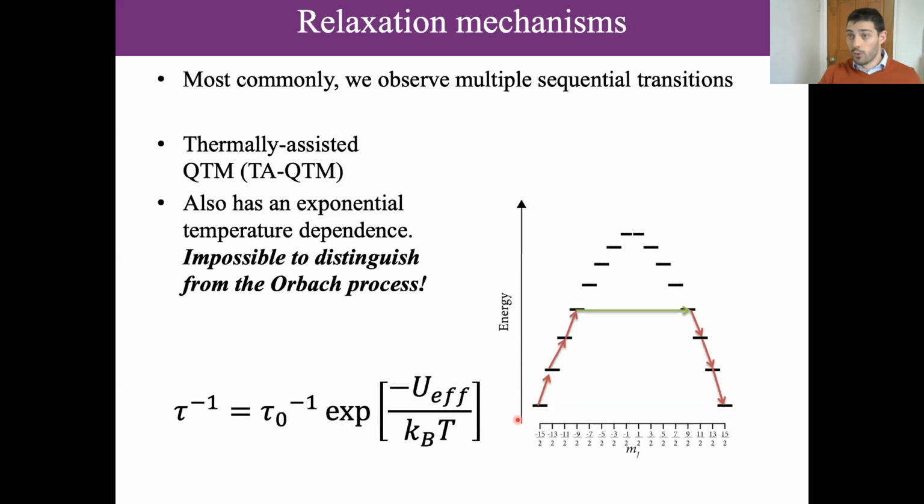Of course, it means that we also have quantum tunneling between excited states, and many people think, and it's an open question, whether the barrier that we actually see is indeed just some phonon promotion, then a tunneling event, and then phonon emission. And that would have an identical dependence on temperature, because this intermediate process is temperature independent. So we couldn't distinguish the two from an experiment.